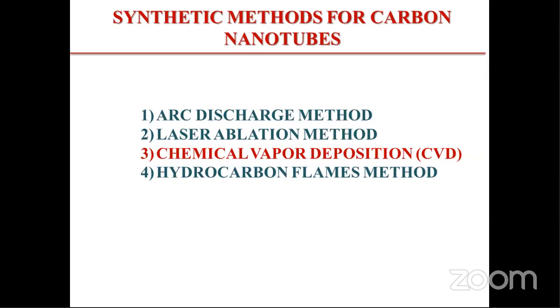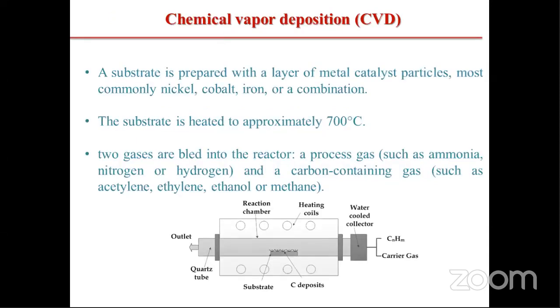In the chemical vapor deposition method, initially they prepare a substrate with a layer of metal catalyst particles. Most commonly used are nickel, cobalt, iron, and a combination of any of these three. Look at the temperature to which they are heated. They are heated to a very high temperature, up to 700 degrees Celsius. This is how the experimental setup would look. Two gases are passed into the reactor: a process gas such as ammonia, nitrogen or hydrogen, and a carbon-containing gas such as acetylene, ethylene, ethanol or methane.